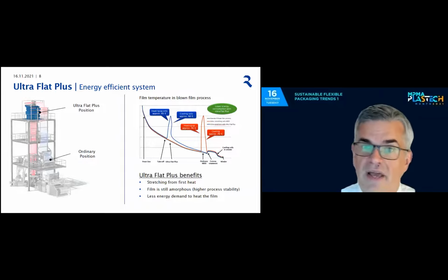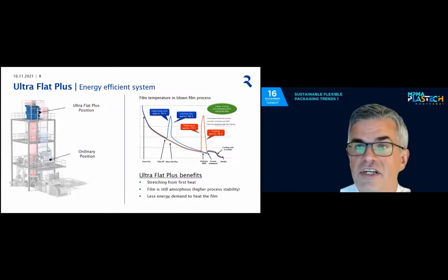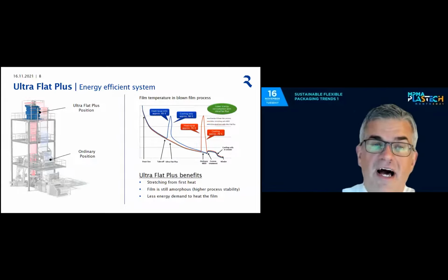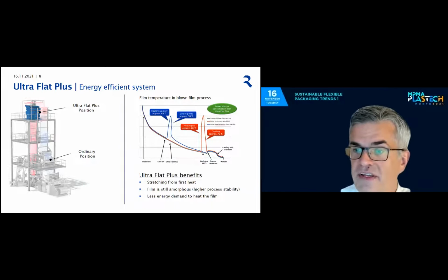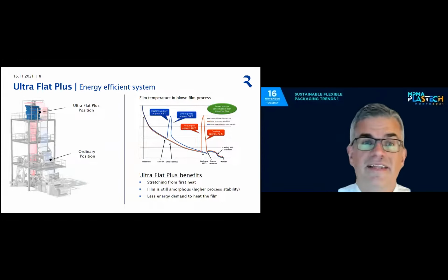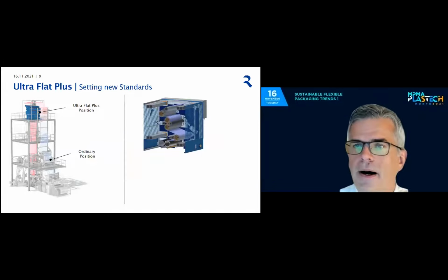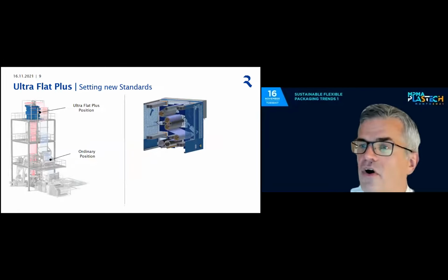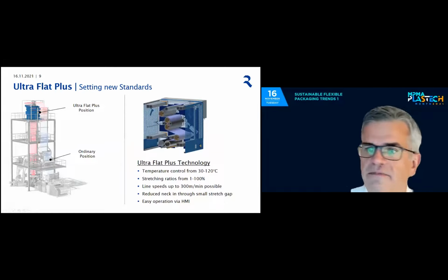So the UltraFlat Plus, this tool for stretching up to 100%, has the same benefits as the UltraStretch for stretching at high rates. We use first heat, the film is still amorphous, less crystalline, and I need less energy to stretch. This system contains only 4 stretching rollers: 1, 2, 3, 4. This is the nip rollers. Here you would have the A-frame. One for heating, a second one for heating, and then I do the stretching between roller 2 and 3, and the last one is used for cooling.